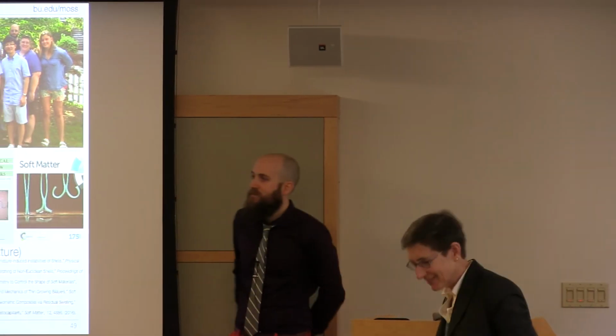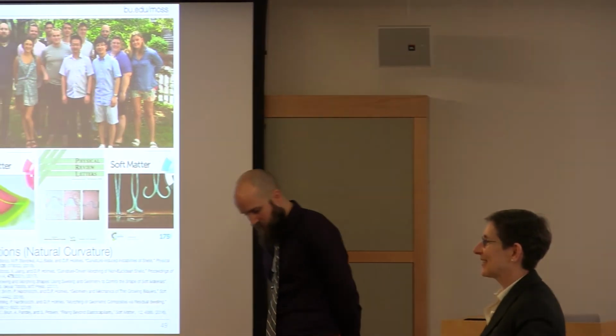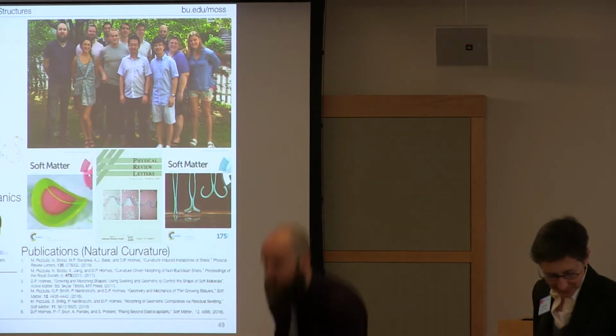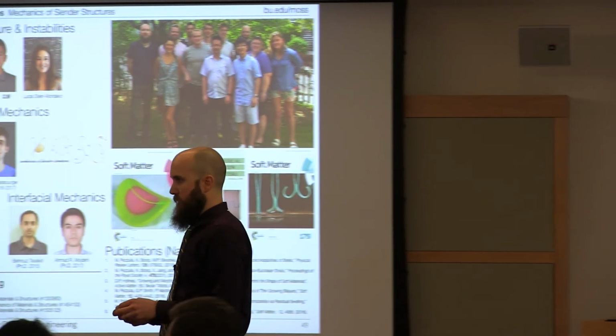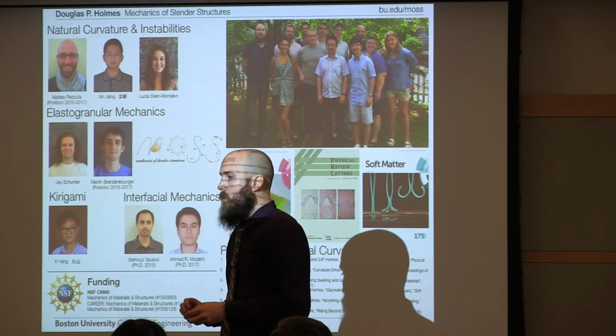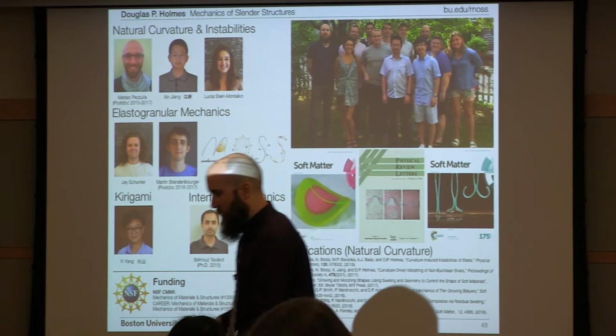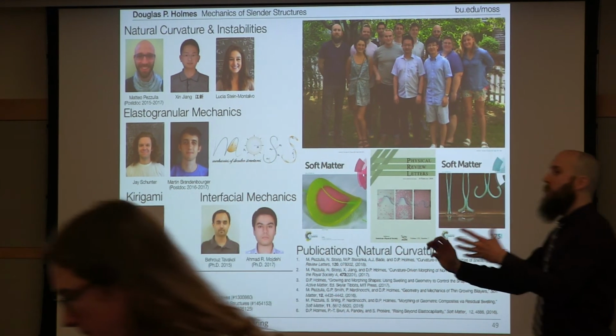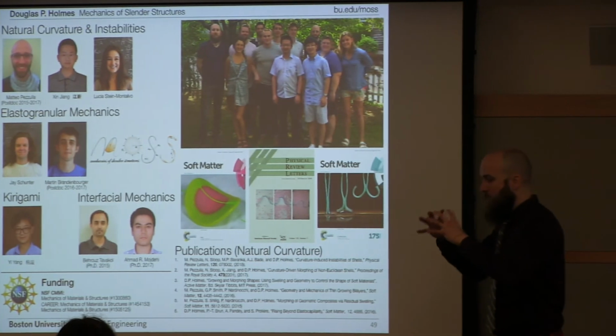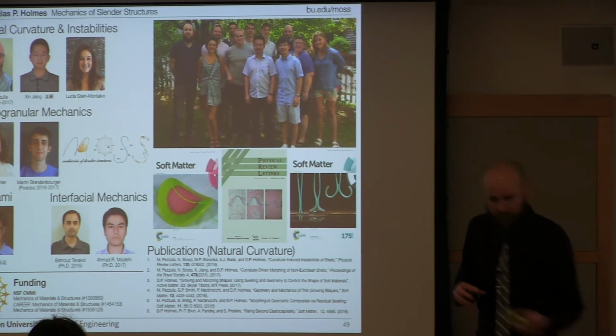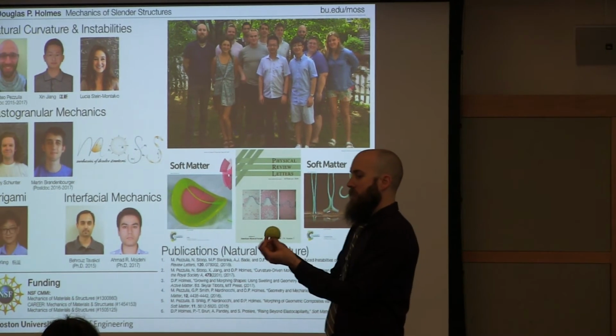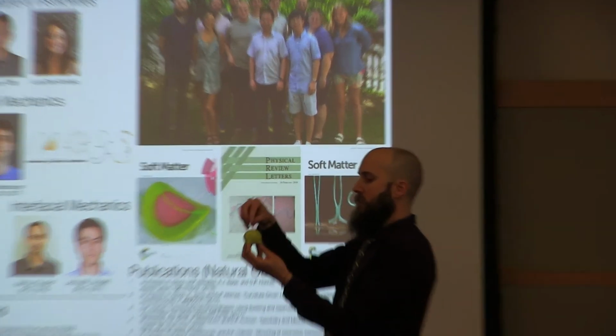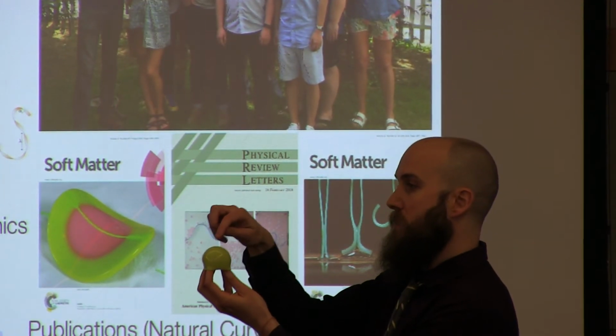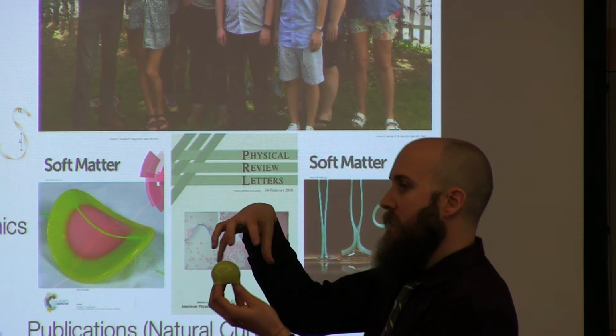Go ahead. So when you're stiffening your spherical shell against buckling, which curvature are you adjusting? We adjust the natural curvature of the shell. What that means is we apply a stimulus that will locally, yeah, perfect. You can imagine I have this thing clamped at its edges, and I apply a stimulus that locally tries to make this point on the material bend a little bit more.